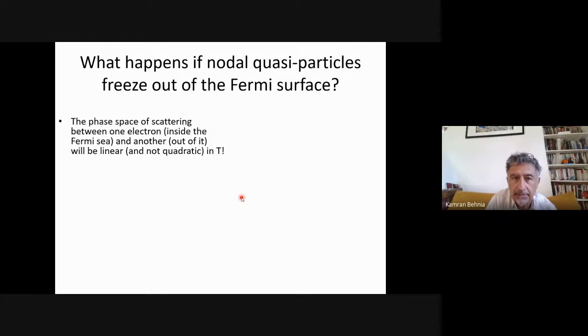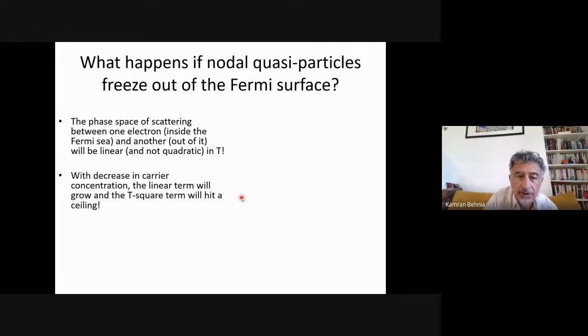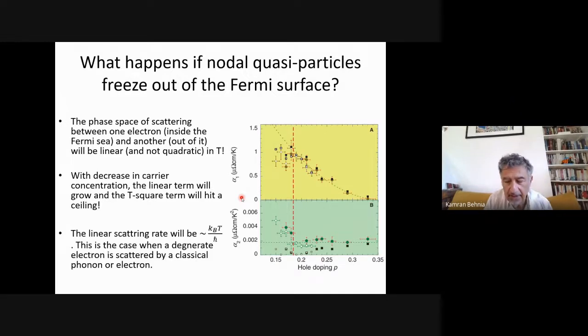Now, if this happens, then the reason T-square resistivity ceases to be accurately valid below this scattering time is this: we are in presence of a system in which a subset of carriers are no more part of the Fermi sea. This will, of course, generate a linear term. The reason is very simple: the reason you have T-square resistivity is that both electrons belong to the same Fermi sea, and you are supposed to employ the Pauli exclusion principle twice. If one type of electrons is classical, then you would expect a T-linear resistivity. This is what happens when degenerate electrons are scattered by classical electrons, or degenerate electrons are scattered by phonons above the Debye temperature. So this is the end of my talk.